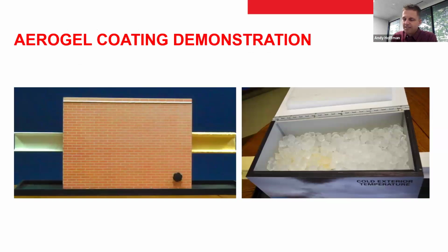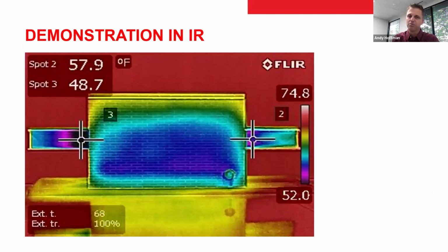So here's just a down and dirty demo that we'll take to trade shows. It's just a 3-foot continuous I-beam where half of it has the aerogel insulation coating, the other half just has an epoxy primer. We'll fill the chest with ice to simulate the interior of the building on a really cold day outside, punching through the walls of the building to the interior space. We'll take the imaging cameras again to highlight the difference in the surface temperature. In this case, you're seeing about a 10-degree delta between the epoxy primer side and the aerogel insulation coating side. This is a really good demo to take to trade shows because you can certainly feel a much bigger difference, but this just highlights the difference with the FLIR camera as well.